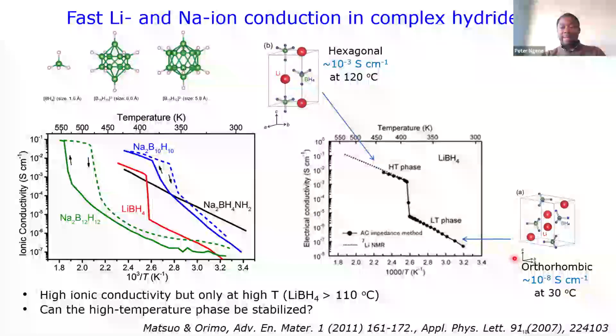So what we do see here is that there's a phase change. This material goes from the orthorhombic phase to the hexagonal phase, associated with a significant increase in the ionic conductivity. And of course, it's an Arrhenius kind of behavior, because of the energy you need to create a defect, and more defects can be created at high temperature. So most of these electrolytes only show high conductivity at high temperature.